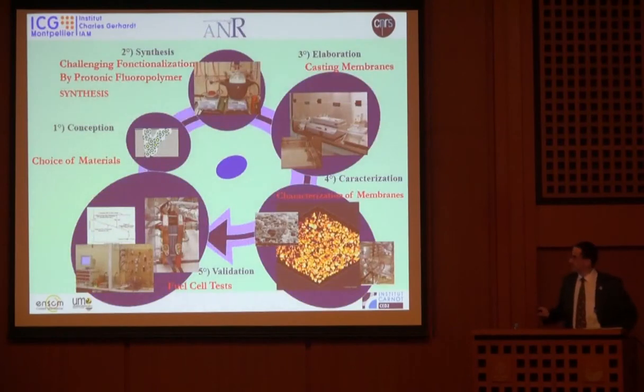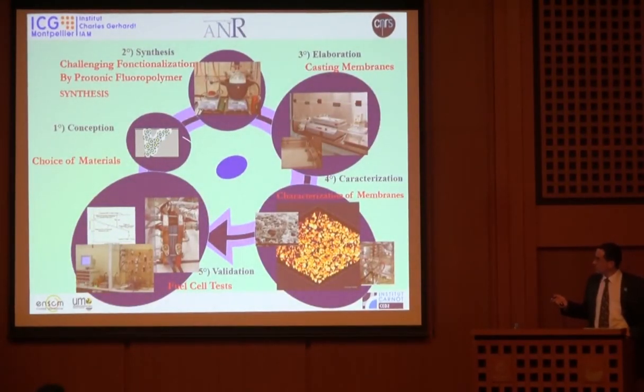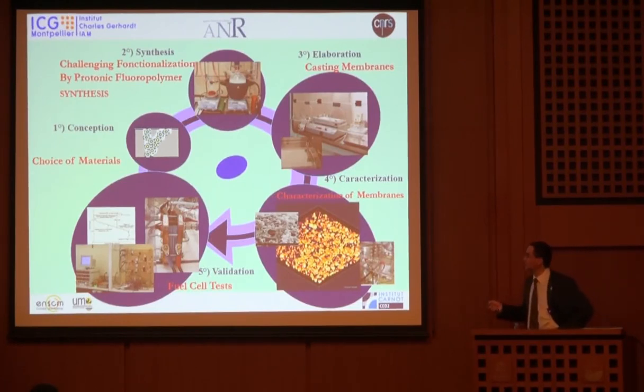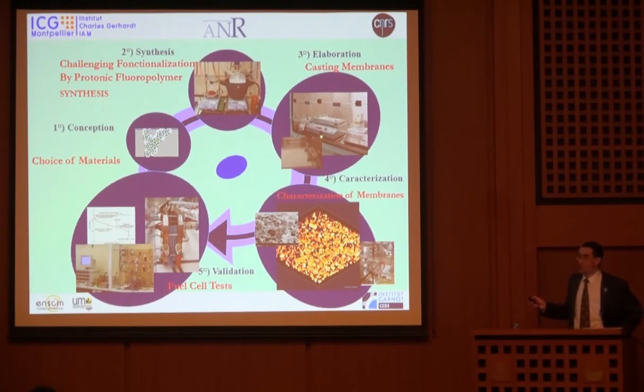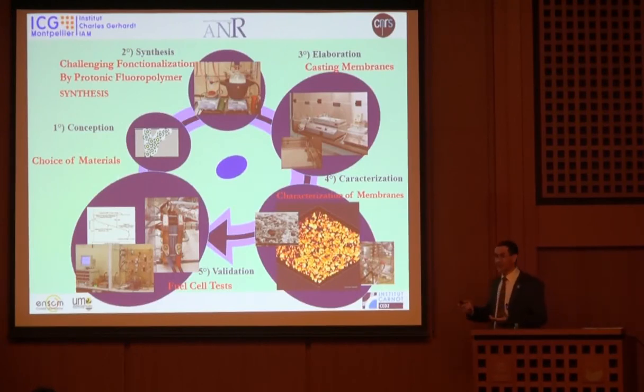So one example was developed at the Atomic Energy Commission, where this group tried to make some functionalization of nanofillers, just like silica, and to put sulfonic acid groups on the surface, and then to blend with some PVDF or even other copolymers in order to make some membranes. This is a fume cupboard in which you do the evaporation, the casting. So you have to design how to mix inorganic material and a fluorinated material, which are not very friendly, but in specific conditions, there is a patent on that, it was possible.